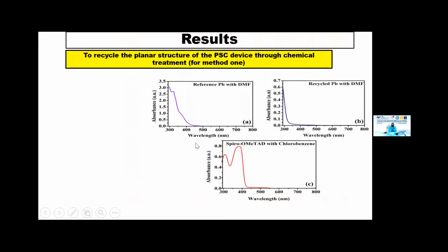Not only that, we use another analysis like for the DMF solution. We use UV, and we detect the hazardous material. For example, we use UV-Vis. We analyze this, and we detect the lead presence. We can see the lead because we use DMF. If we use only DMF, there is no signal, but we got the lead. This is the reference we use. We dissolve fresh lead with DMF solution, and also we check our separated solution. So there we can see that the signal from 400 to 500 is the same. So we can ensure the lead presence. And also for the spiro-OMeTAD we use chlorobenzene solution, and we compare it. It's similar.